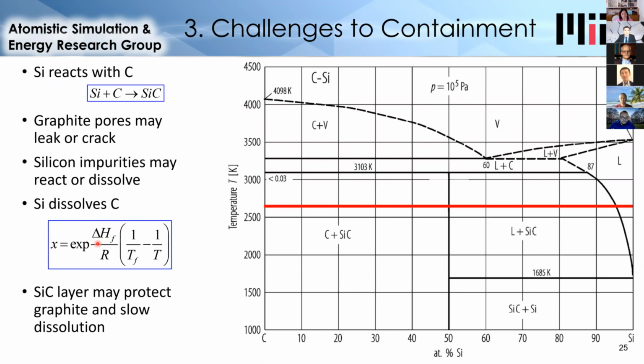the bond strength, which is indicated here by the formation enthalpy, and the difference between the temperature you're at and the temperature that the material melts or decomposes. So here we're considering silicon carbide because that's the surface the silicon is exposed to, which decomposes up here at 3100 Kelvin. So we're not that close to melting or decomposition, but this curve shows the effect of the solubility. So as you increase temperature, solubility increases.